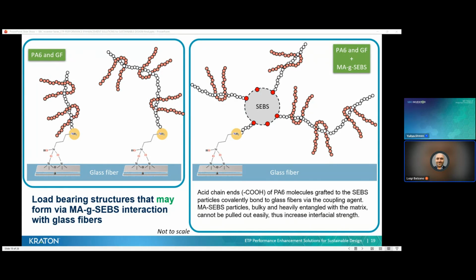Now, going to the picture on the right-hand side of the screen, when we introduce malleated SEBS in the system, we are introducing elastomer particles with the polyamide 6 molecules sticking out of their surface and terminated with the acid end groups. These acid end groups of the polyamide molecules tend to react to the coupling agent. In this way, the SEBS particles end up directly linked, pinned, connected to the glass fiber surface.